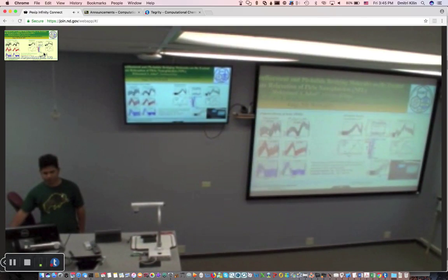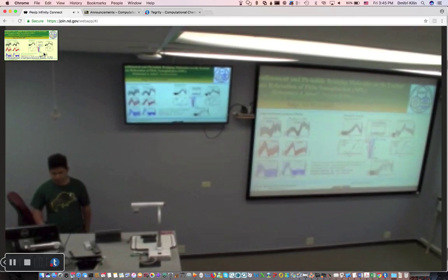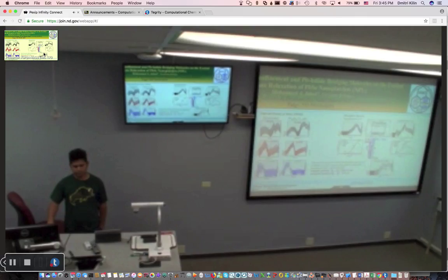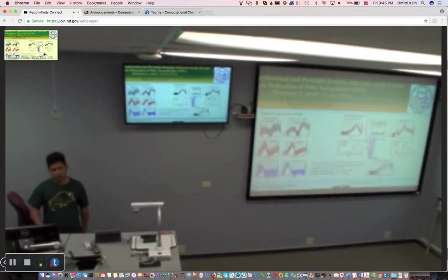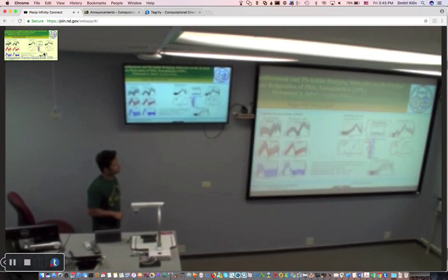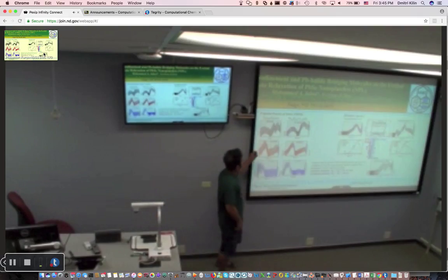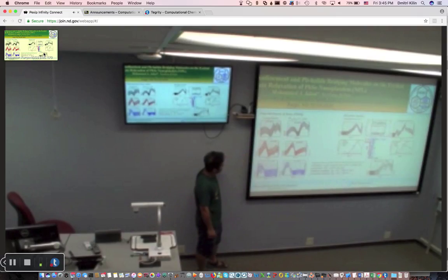If you look at your nanoplates versus quantum dot, it looks like the nanoplate spectra have more discrete, more clear peaks compared to the quantum dot. But the confinement should make the splitting between levels more significant, so you expect these peaks to be more narrow and more discrete in the quantum dot rather than the nanoplate. It's maybe because this is the projected DOS for lead only, but this is not the full DOS. The same for the H, showing very clear peaks, while in your quantum dot they are more smooth, more spread.